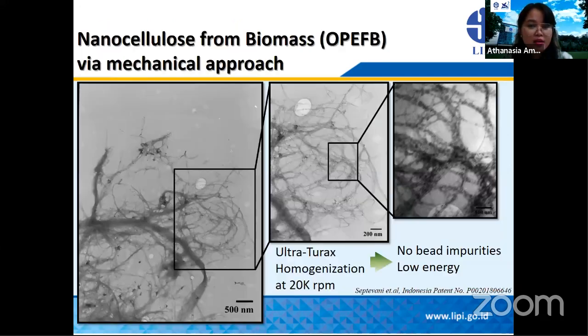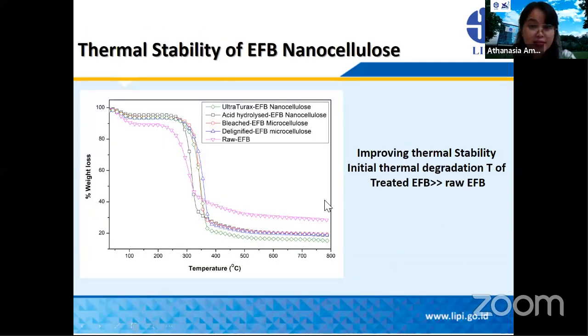So we also do the production of nanocellulose via a mechanical approach. We use ultra-turrax homogenization at high speed, about 20 kRPM, and we can produce nanofibril structures. This is quite interesting, because it can give a potential method to develop cellulose nanofibers, because first of all, there will be no bead impurities compared to other mechanical methods such as high energy bead milling. It also offers lower energy required during the process, which is very useful to reduce the cost of production. So this is the thermal stability of the nanocellulose from oil palm empty fruit bunch. We can see the improvement of the thermal stability along the process.